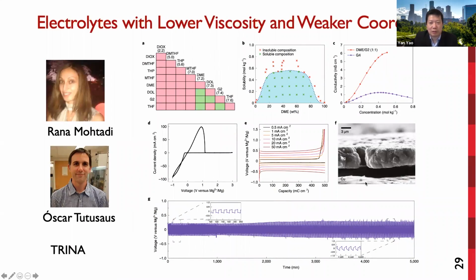While the fast kinetics has been shown earlier, the cell power is still limited by the mass transport in the MACC G4 electrolyte. So Rana and Oscar from Toyota tried a variety of solvent blends and found several mixed solvents that provide much better solubility. Here we use DME and G2 as a mixture, which provides the best solubility, reaching a 6-fold increase in ionic conductivity. We have observed a mixed solvent shell of magnesium from NMR studies. Cyclic voltammetry shows 99.9% Coulombic efficiency, reaching an impressive 100 milliamps per centimeter squared. So this is 10 times higher than that of the MACC G4 electrolyte.